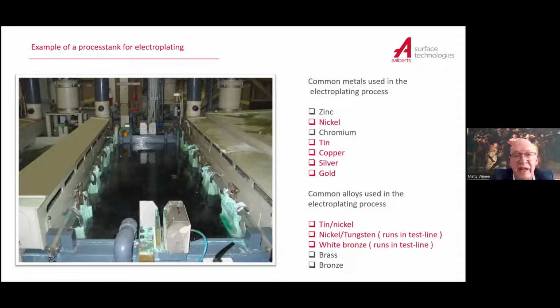Then in the middle, you have the electrolyte. And the electrolyte contains, in principle, two things. First, it contains the metal dissolved, the ions of the metal which you want to plate, because otherwise it takes too long to dissolve on the anode and go to the cathode, so the metal ions are in there. So if you want to plate nickel, you have nickel ions. If you have tin, you have tin ions. And they contain an anion, which is dissolving the nickel metal on the anodes. That means that you have a minimum of two chemicals in the bath, and you have the metal on these sides. In the middle, you have an opening in which you can hang a bar, and on that bar, the parts are hung for plating.